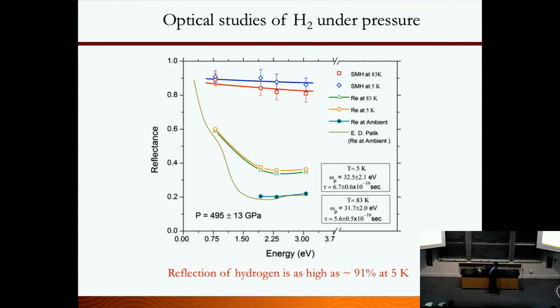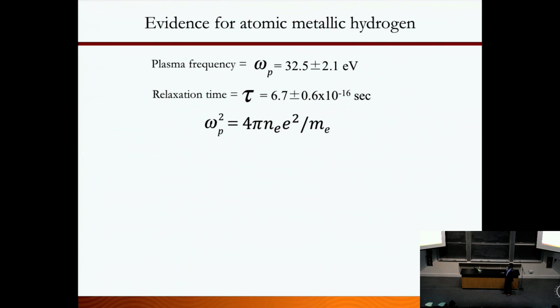The data that you're seeing here is a Drude fit for the different wavelengths. We did it from 400 nanometers to 1550 nanometers. The blue dots are the 5 Kelvin, and red are the 83 Kelvin reflectivity. Reflection is as high as 91% at 5 Kelvin. For comparison, we measured the reflectivity of rhenium. This curve is the ambient condition measurement done by others, and these are the measurements done by us. They match fairly well, indicating that whatever we are observing is a real measurement. From there we extracted the values for plasma frequency and relaxation time. The plasma frequency happened to be 32.5 electron volts, one of the highest known plasma frequencies, and from there we can get the electron density.